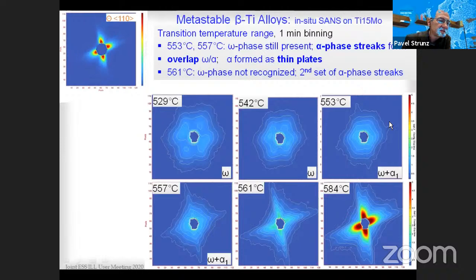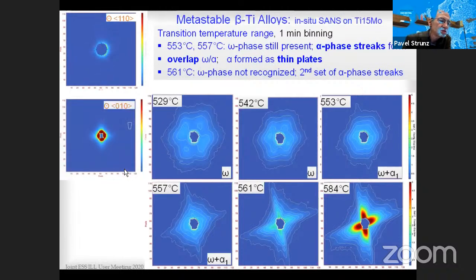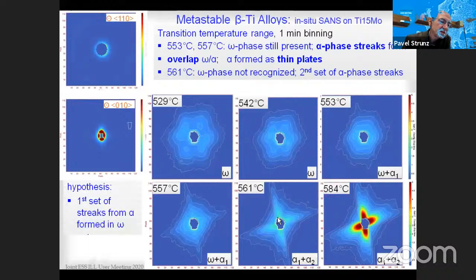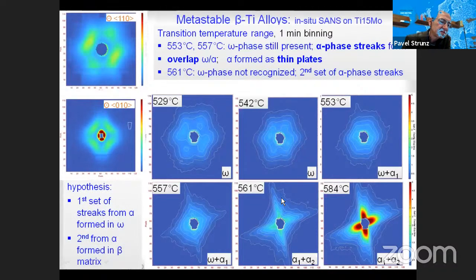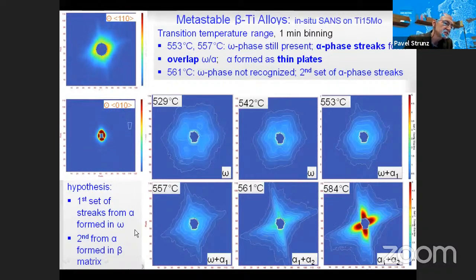That means that we have an overlap of omega and alpha. And also, it's sure that alpha forms in thin plates because we see streaks in this orientation, but not in this orientation. When we go further to 561, we see that there is already no omega, but there are streaks of alpha. But there is another set of streaks from alpha, better visible at 584 at high temperature. So that means that we have two sets of streaks. The working hypothesis is that the first set of streaks comes from alpha, which is formed in omega, while the second from alpha, which is formed in the beta matrix.